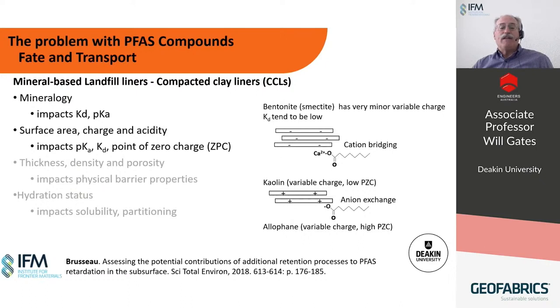The minerals such as allophane have a variable pH-dependent charge, but have a high point of zero charge. That means the pH at which the net variable charge is zero is fairly high. Then we can expect that direct ionic interactions of the anionic forms may occur, because the surface charge is net positive and the PFAS is predominantly in its anionic form. So for example, allophane at a pH of 6 would be net positive, but most PFAS compounds would be anionic.